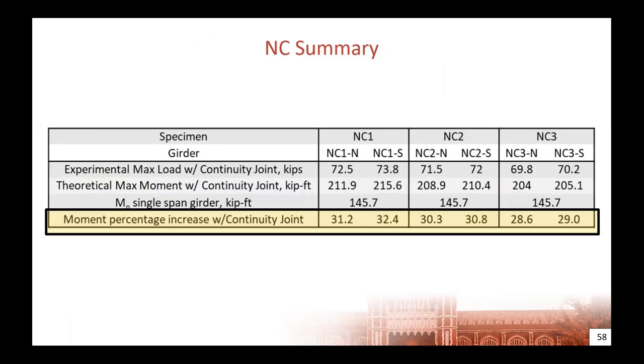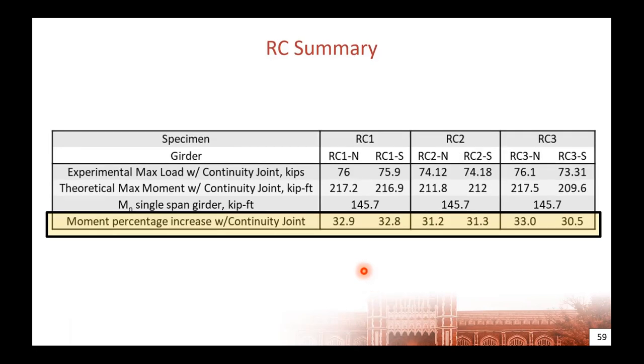And then for both sets of specimens, both new construction and retrofit construction, if you look at this bottom row, we saw about a 30% increase in moment carrying capacity when we added that continuity connection relative to the simply supported beams. So from our laboratory investigation, we saw that at least for ultimate load capacity and developing continuity between our beams, the UHPC connection performed very well.